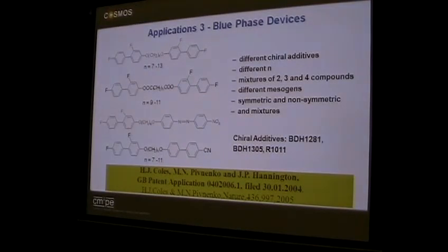But that's sort of part of the tutorial nature of this presentation. Again, I didn't stress it earlier, we use chiral additives, 1281, 1305, R1011, very high twisting power. So you only need a few percent to stabilize the system. You tend to use a mixture of two or three of these, so that if you have solubility problems, which you sometimes might have, you can get to your 3% by adding 1% of each. Sort of just to help the system along.